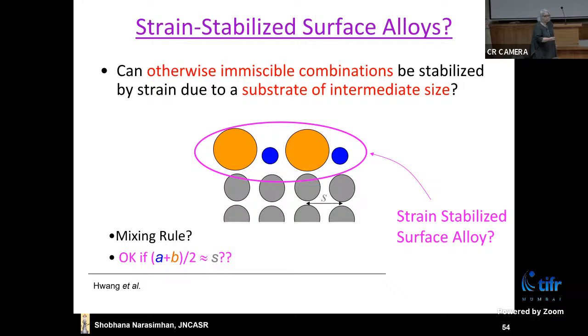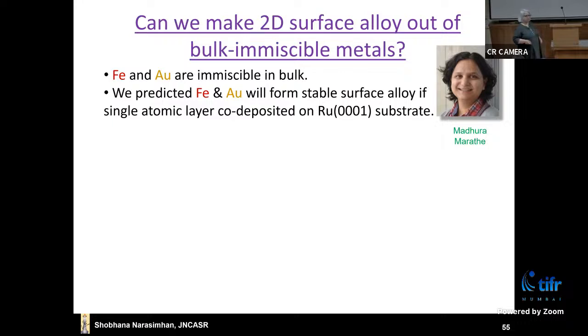So there's this experimental group in Paris, headed by a scientist called Sylvie Rousset. And she approached me and asked if our group could help her design a system where they would succeed in this. I'm skipping the details of how we narrowed the possibilities down, but the calculations were done by my student Madhura Marathe, and she said if you take iron and gold, now iron and gold basically don't mix in the bulk, but if you take iron and gold and deposit just one layer of them on a substrate of ruthenium, then it will form a surface alloy.